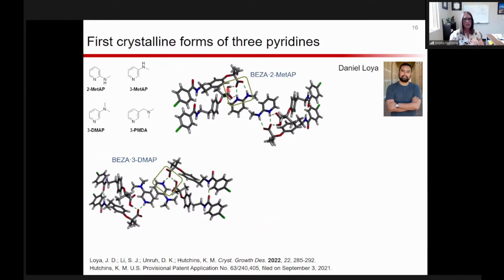So we actually had the first crystalline forms of 3 of the pyridines out of the 4. The 3 substituted pyridines had never been incorporated into a solid form before, likely because they are difficult to crystallize. So I'm just going to show you quickly the X-ray structures. They are a little bit complicated, but I'm just going to highlight some key points. With the 2-methylamino-pyridine, you can see a 2-point hydrogen bond there with the carboxylic acid of the bezafibrate. The bezafibrate is partially protonated, partially deprotonated.